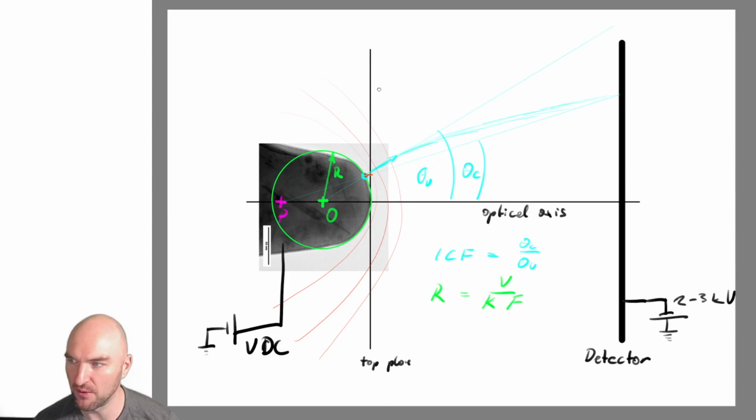Here in Erlangen, we have one atom probe that's actually an electron spectrometer, where our friends over at physics have gone to great lengths to shield any electrostatics from the internal of the chamber. And the reason is because usually they have very low energy electrons flying around in there that they don't want disturbed. And in this case, you don't have any of these effects. The imaging stays relatively constant throughout the experiment. Of course, we haven't done very large experiments in there yet, so I don't know if the change in the shank environment would do maybe something, but certainly the detector doesn't do anything in this case.